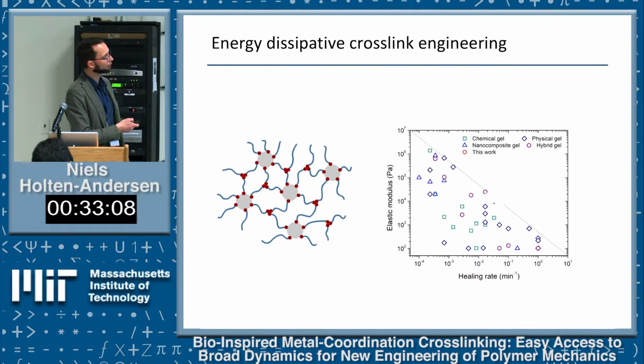We reported the elastic modulus, how stiff the materials are, and how quickly they self-heal. You can see there's some sort of trade-off: if you have very stiff materials, they don't heal that fast, or if you have fast healers, they're typically not that strong. And that's built in if you only use one type of cross-link in your material.